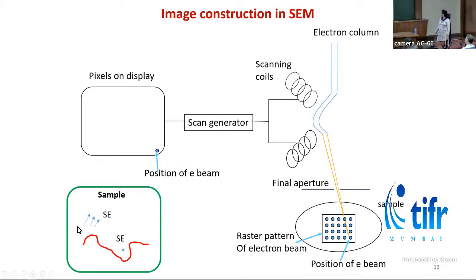If the sample has topography, that means it is rough and it has some hilly regions and some valley regions. There will be more secondary electrons reaching the detector from these hilly regions, so these will look bright in the image. And fewer secondary electrons can reach from these valley regions, so these regions will look dark in the image. So that is how the grayscale is created in SEM.